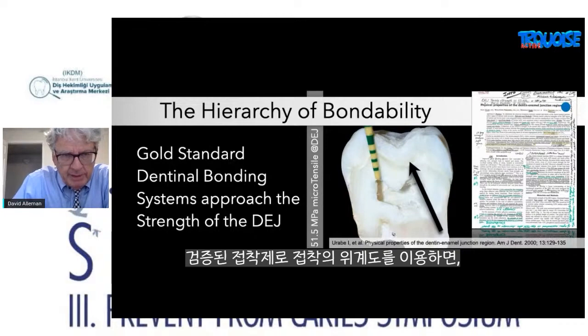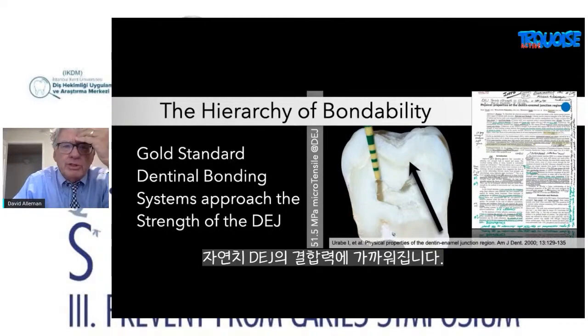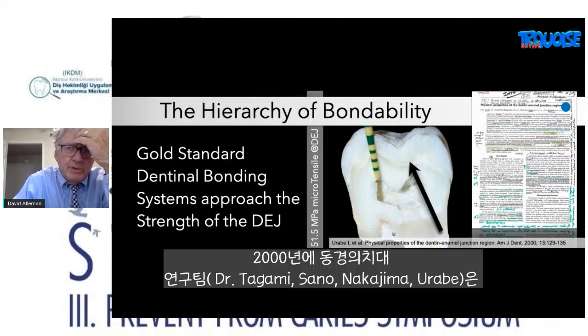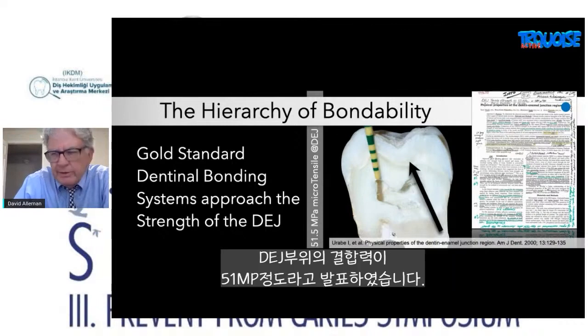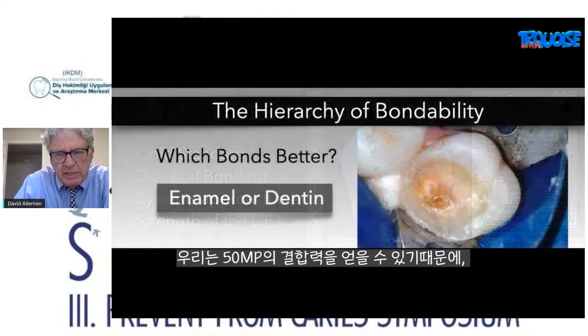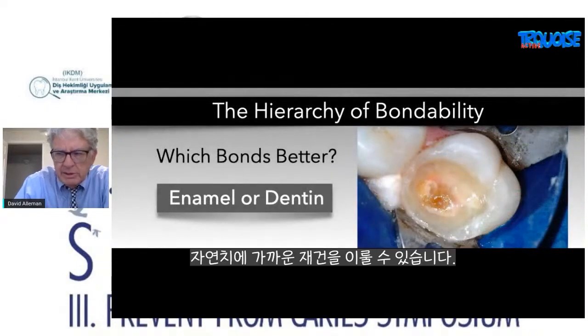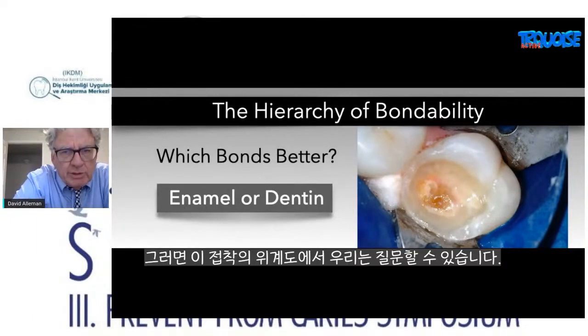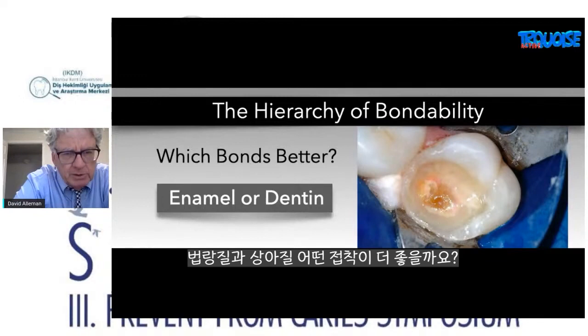And so this hierarchy of bondability with gold standard bonding systems approaches the strength of the DEJ. This paper in 2000 out of the Tokyo Medical and Dental University team, led by Dr. Tagami and Dr. Sano, Dr. Nakajima, Dr. Urabe, showed that there is a bond at the DEJ area of around 51 megapascals. And because we have the ability to get to 50 megapascals, we can have a reconstruction that is like a natural tooth. So in this hierarchy of bondability, we ask the question, which bonds better, enamel or dentin?